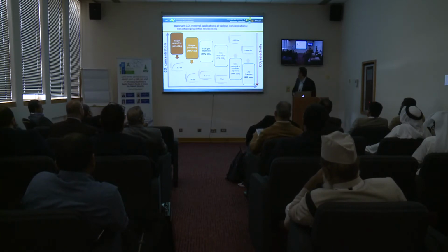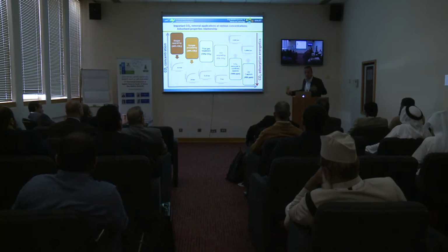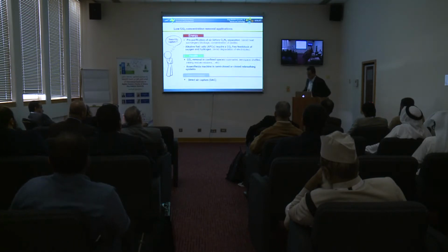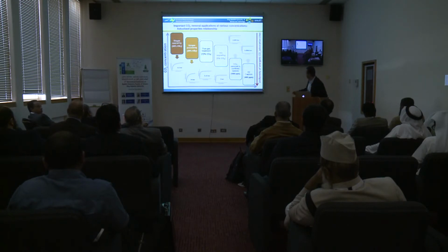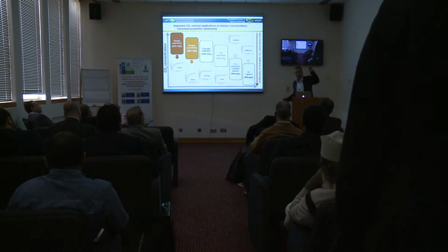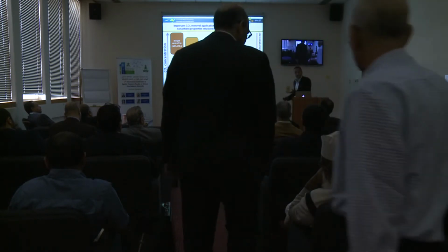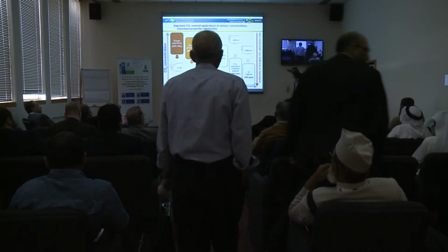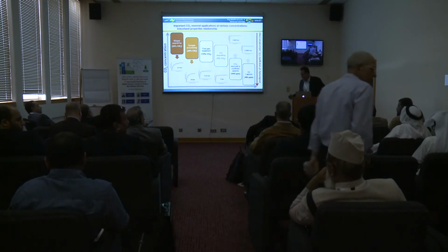Of course, this is correlated to adsorption energetics. Here you want to have this material to absorb strongly, but also not as strong as chemically, so you can remove it by reducing your pressure. And most importantly, you need to have what we call uniformity of energy sites here. So you don't want to have only few sites that absorb your CO2, then after those are gone, then you will lose selectivity. So you need to have something that's continuously keeping this selectivity.